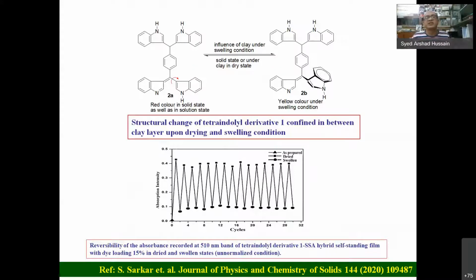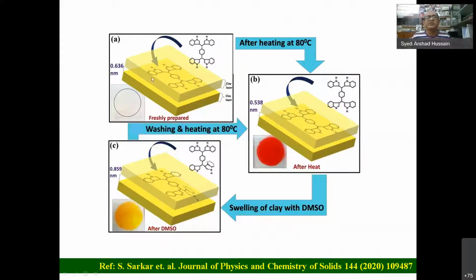This is important. So schematically here we have shown this is the freshly prepared state. Then in dry conditions, you see it's red, and also we measured the thickness with XRD. You see here it's less, so the molecule is almost flattened, and this will extend the pi conjugation also. So red color occurred, but when we swell, you see the gap increases and twisting occurs here, so the color changes.